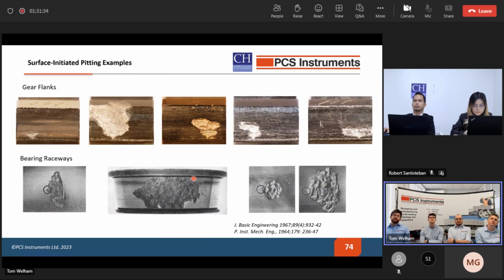So here are some examples of surface-initiated pitting. We see it often has a distinctive shape, this fan shape. The point of the fan, which is located here, often indicates the origin of the crack, and you will see that it will have beach marks close to the origin, where we have these striations where it is stop-starting the propagation. And then towards the end of the pit it'll be a torn surface, where it has propagated very quickly and the material is removed.